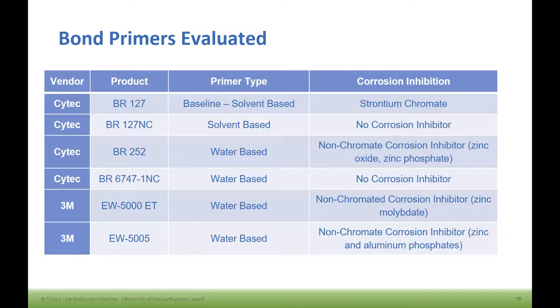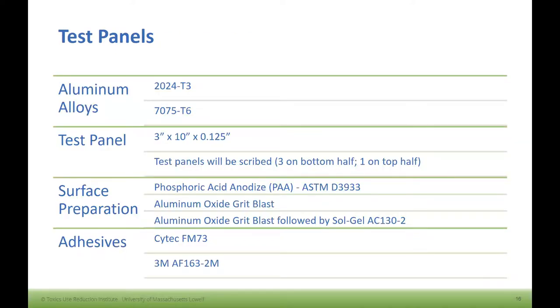For the bond primers, we evaluated six, with one baseline that had hex chrome, the BR-127. We had three that had non-hex chrome corrosion inhibitors, and two products that didn't have any corrosion inhibitor. This time we looked at both 7075 and 2024 aluminum alloys, and three different surface preps. First was phosphoric acid anodized, PAA. Then aluminum oxide grit blast. Then grit blast followed by Sol-Gel. We also looked at two types of adhesives, one from Cytec and one from 3M.